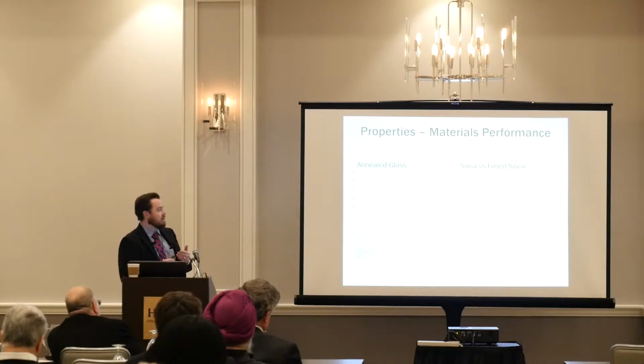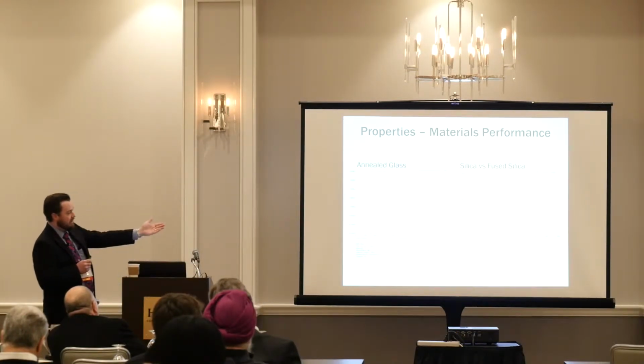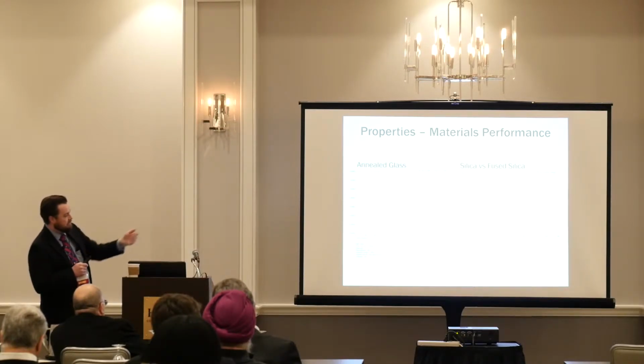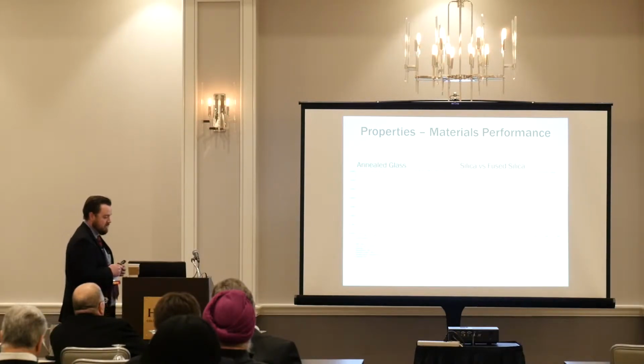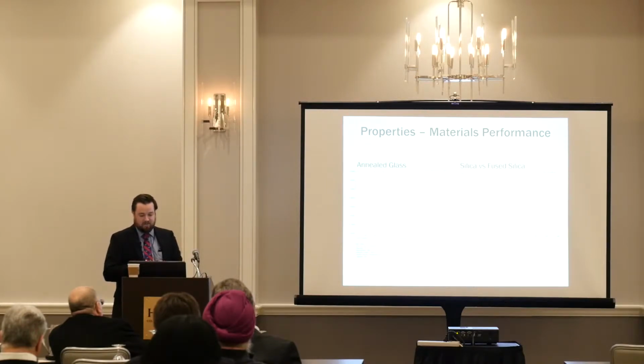On the right side, this goes to show you that the material performance is relative to the material itself. You're looking at silica versus fused silica, very similar materials, but not when you are using them in a large temperature range like this. The fused silica at the bottom hardly makes a move, while your silica goes through a large displacement reaction, and it starts to show you which one you should use for your application. It helps you figure that out quickly.